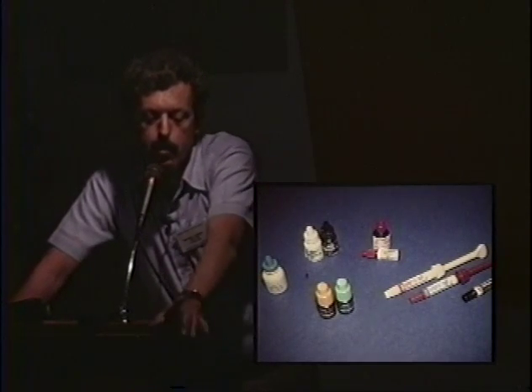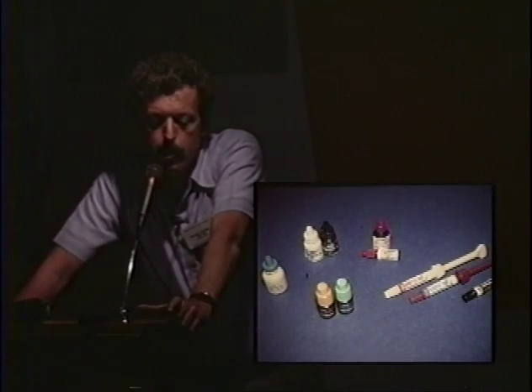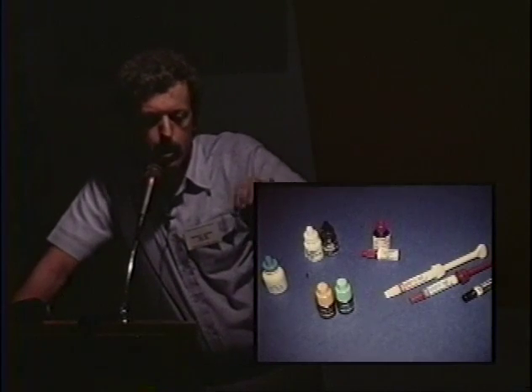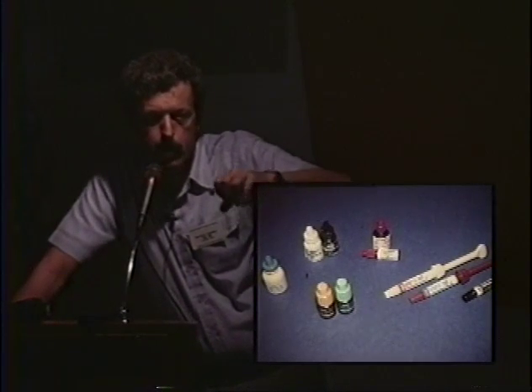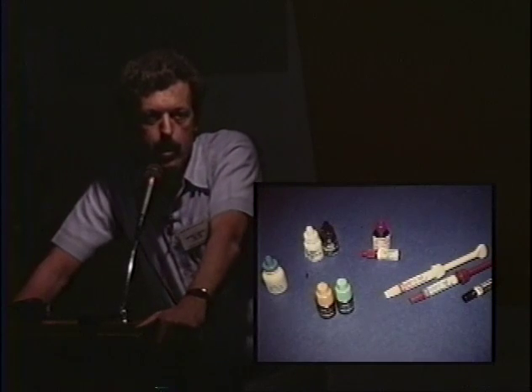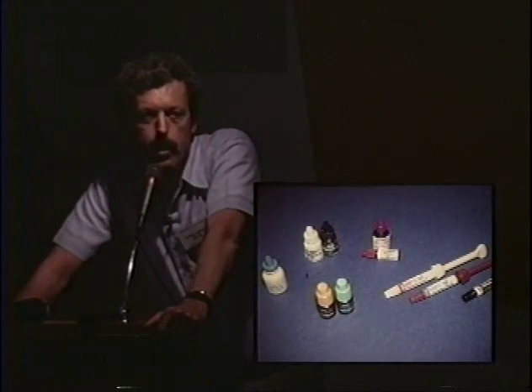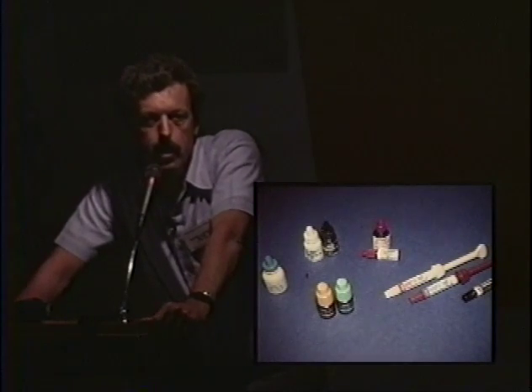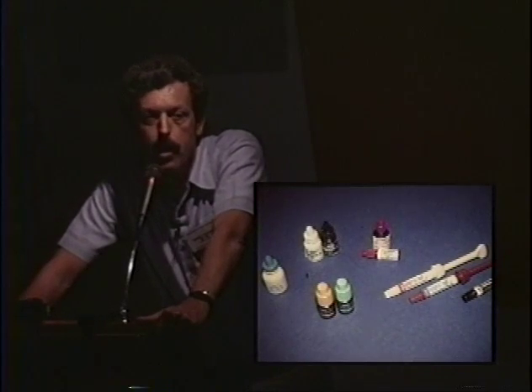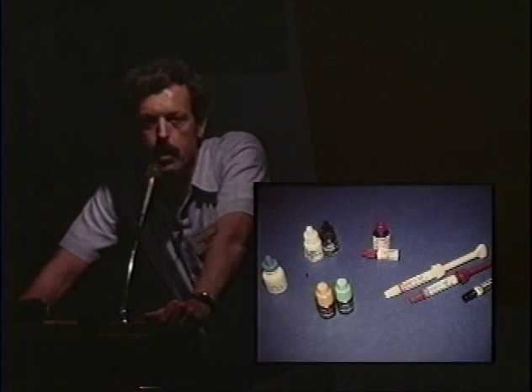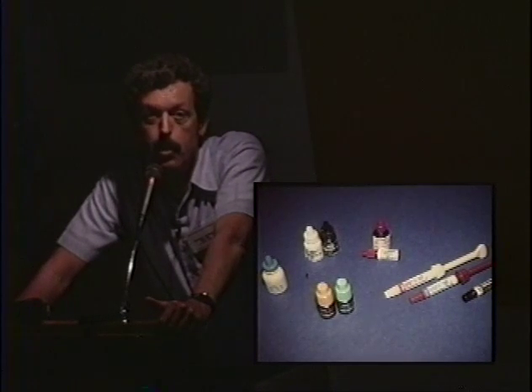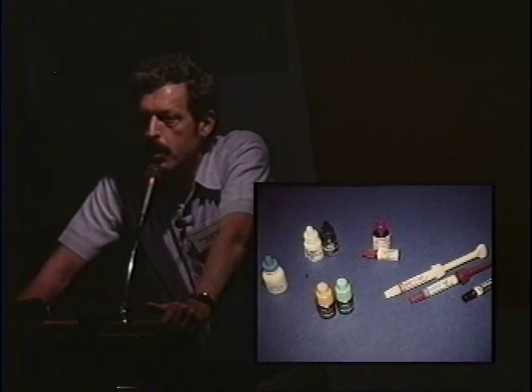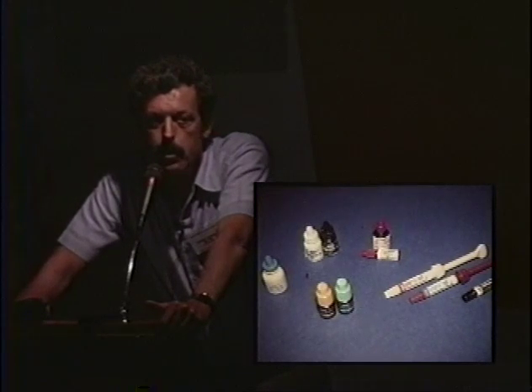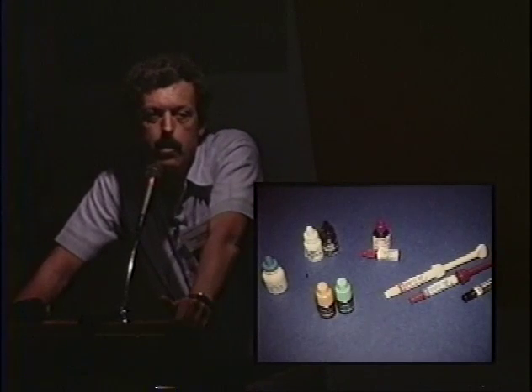And in regard to tri-n-butylborane, if you want to test your catalyst with Metabond, all you do is you take your catalyst and you put a drop on Kleenex, and if it doesn't burst into flames, you've got bad catalyst. It's old stuff. It's pyrophoric. It should at least smolder. And under ideal conditions, it would burst your Kleenex into flames if it's a hot, good, proper catalyst. Okay. If you don't have that activity, I'd put in a couple drops of catalyst. I wouldn't use one. I'd use 2. Maybe 3. Because you don't know how active the stuff is.